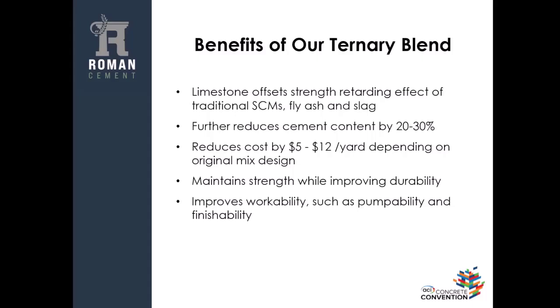They ultimately yield great strength, but early on they have a retarding effect. But by using this coarse limestone powder, it has an accelerating effect, and so they offset, and we get very good results. We can reduce the cement content further from a binary blend by 20 to 30% and get the same or better strength, good durability and workability.